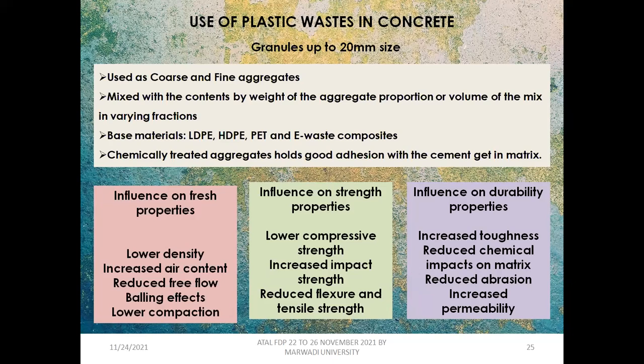in concrete, like the influence on fresh properties. With lower density, there is increased air content, reduced free flow, a balling effect, and lower compaction. These are some of the significant parameters influenced by the addition of granules into the concrete. Then the influence on strength: lower compressive strength is observed, increased impact strength is observed, and reduced flexural and tensile strength.